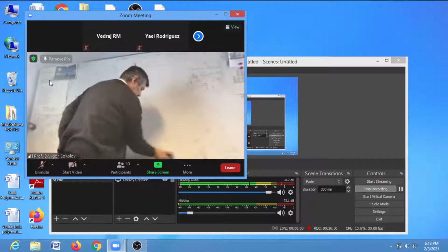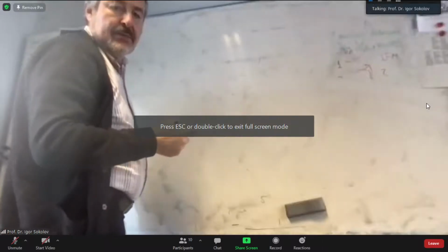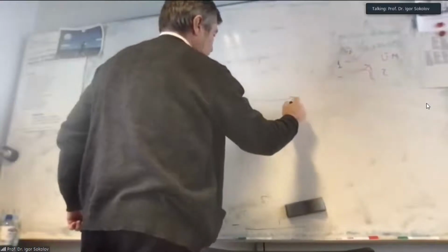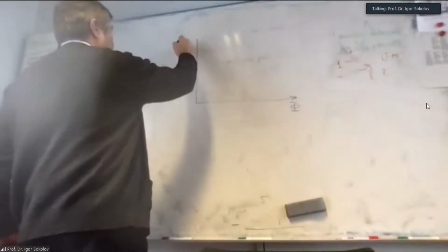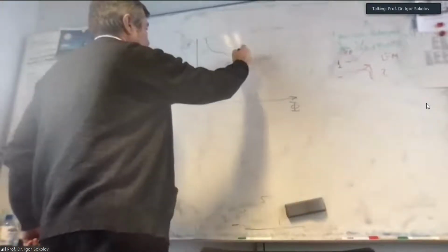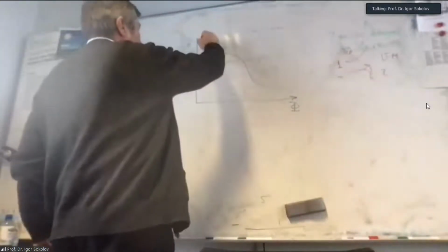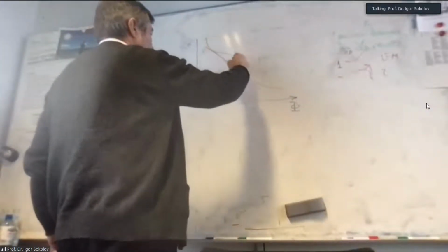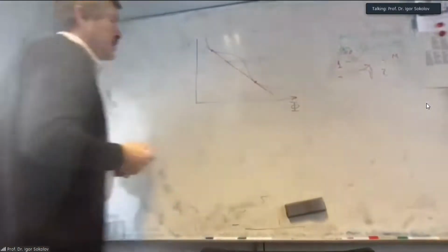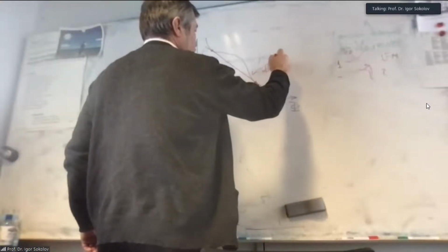So what we had when we discussed how to find a binodal, we had to draw a picture, phi, f of phi, and this could be phi, and it has two inflection points, and then we had to find a line which is a common tangent to this curve f of phi in two different points.